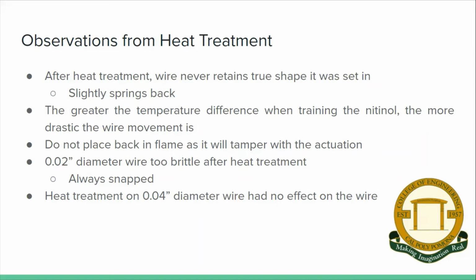Heat treatment of the 0.02 inch diameter wires made it too brittle and it would always snap when straightened. While on the 0.04 inch diameter wires, there would be no effect after heat treatment, most likely due to the fact that we did not reach adequate heat.